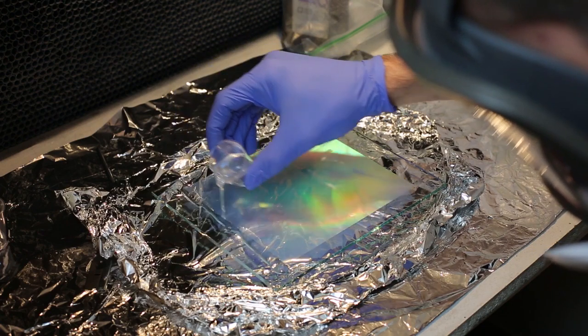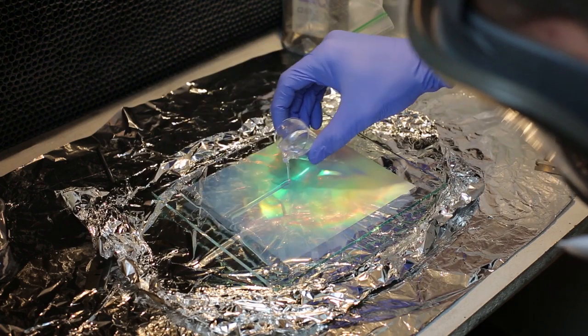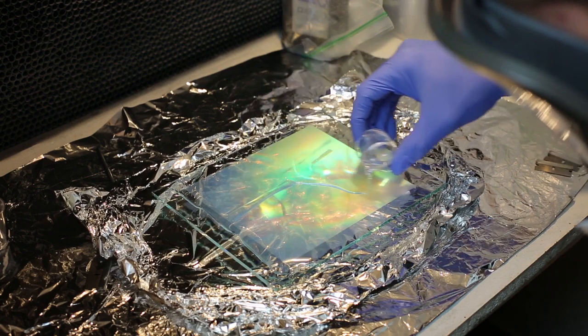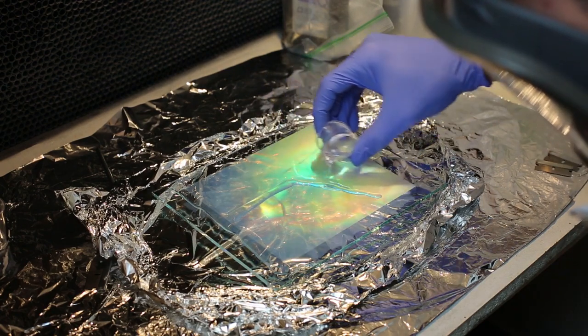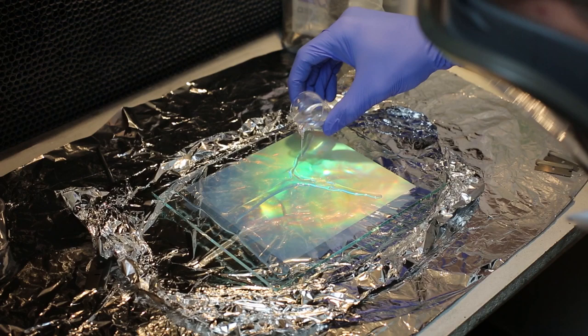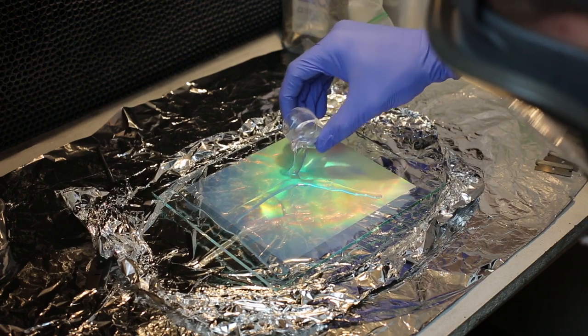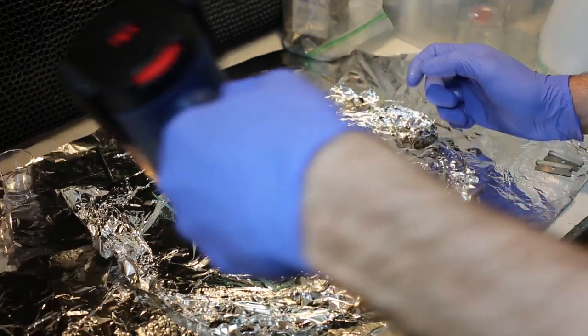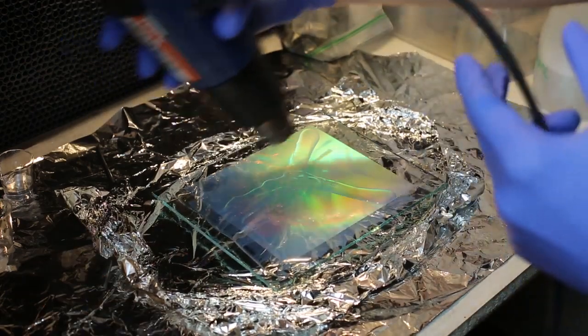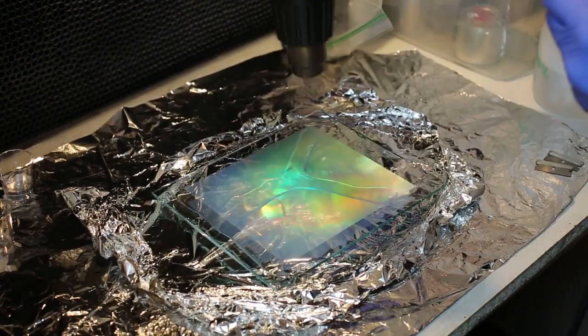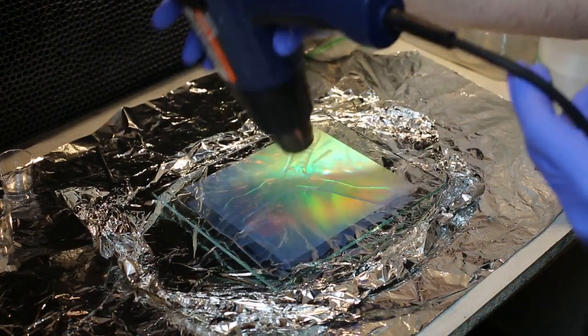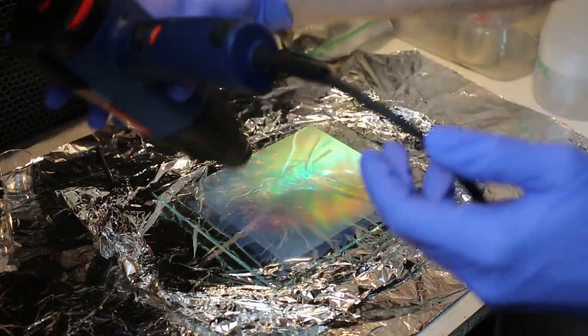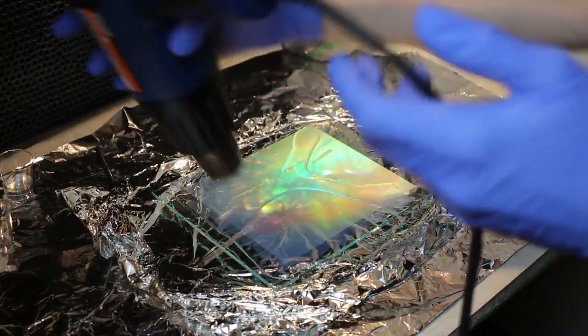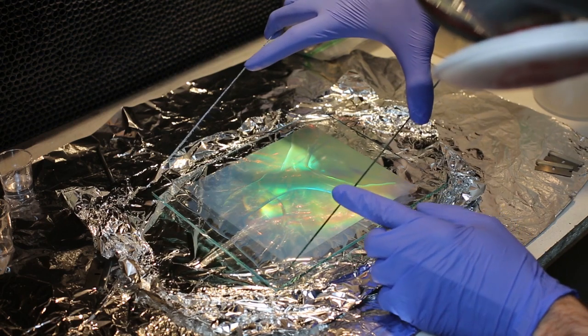The shape of the poured glue should look like a T with 2 legs. I try to avoid making any bubbles. Once the glue has been poured on the glass, I blow with the heat gun over the hologram. This will heat up the glue, which will make it more fluid and at the same time pop most of the bubbles in it. From the drying cabinet, I fetch the cover plate.